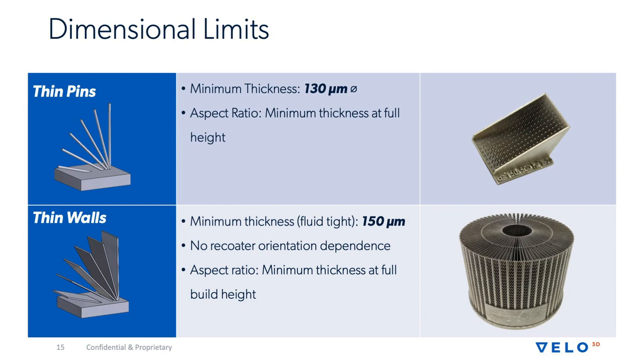Thin walls, a similar case here, though they have rigidity in some orientations, but with other systems, you're limited to the orientations that you can do. This radial heat exchanger type geometry is showing that the walls have uniform thickness and they're not being distorted regardless of its orientation relative to the recoater, because there is no interaction, again, between the part and the recoater.